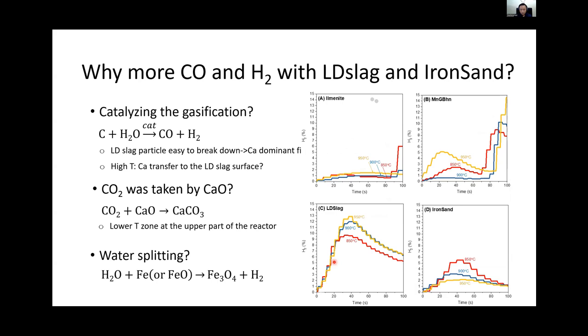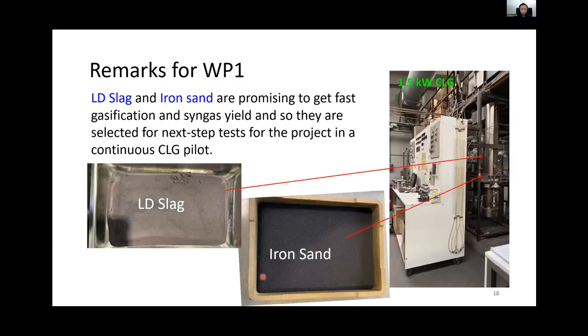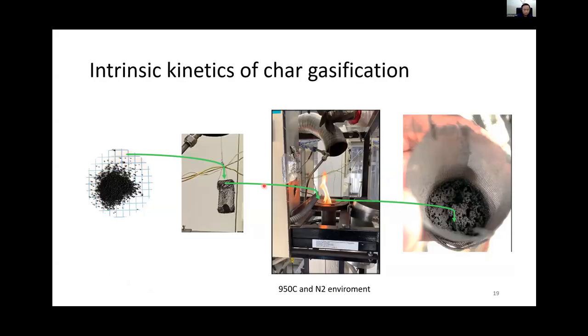A third could be the water splitting. This was found more relevant for LD slag. So you can see from these figures, LD slag and iron sand, when reduced oxygen carriers were exposed to steam before they start the fuel. So what water splitting means is steam plus iron, we get hydrogen. But anyway, LD slag and iron sand are promising to get faster gasification and syngas yield. And so they are selected for the next step test for the project, a 1.5 kilowatt CLG pilot.